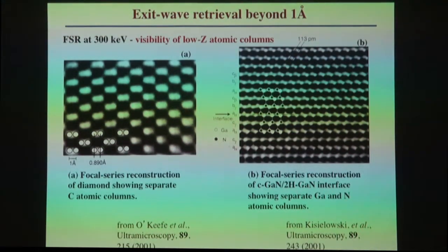And if you push it to a higher voltage, and this is from the work of O'Keefe and Kisielowski, a pair of papers published in Ultramicroscopy, here is diamond in the 110 projection, showing separation of the diamond dumbbells, in this particular case the dimers, at 0.89 angstroms.